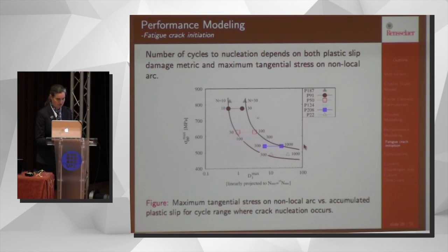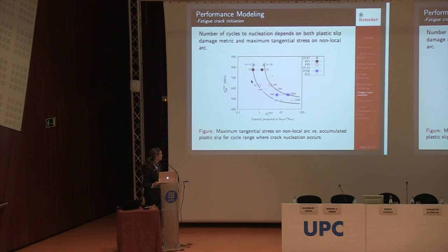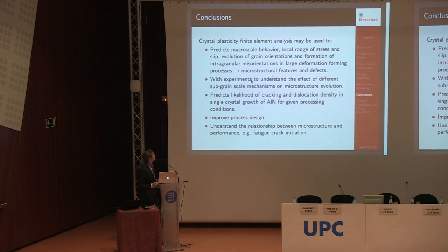And the important thing is that we found this sort of a relationship. Now, the experiment looked only every few cycles. They stopped the experiment and looked where the cracks were. So we know, for example, here, this one nucleated between 30 and 100 cycles, here between 10 and 30. So the main thing that we found was that the number of cycles to nucleate depends on both the plastic slip damage metric and the maximum tangential stress on some non-local arc. In this way. So just some quick conclusions.